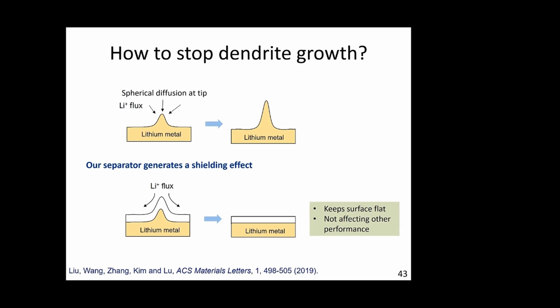Now, our separator generates a shielding effect. When the dendrite pushes our separator, the shielding effect will cause lithium ions to deflect away from the tip, therefore causing the lithium metal to grow flat.